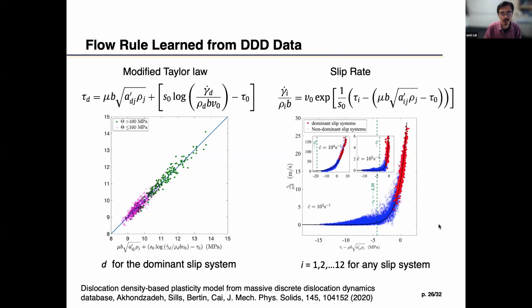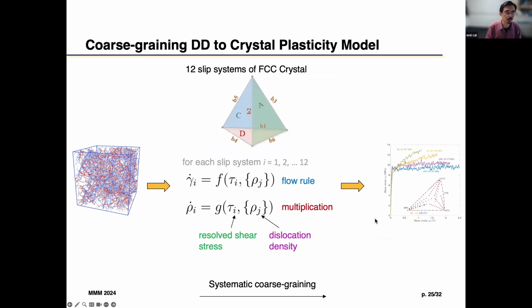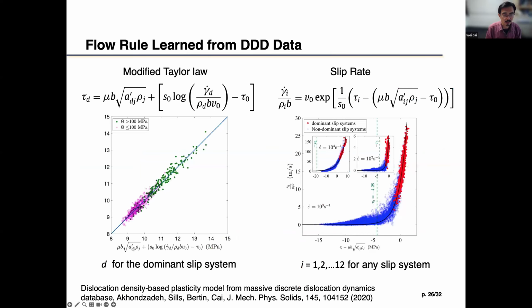But of course, you can see that there's still a lot of scatter, and that is because this coarse-grained model is a much more simplified model than the original one, right? So the next step would be to see whether we can develop a more sophisticated model on top of this to explain away the remaining variance.